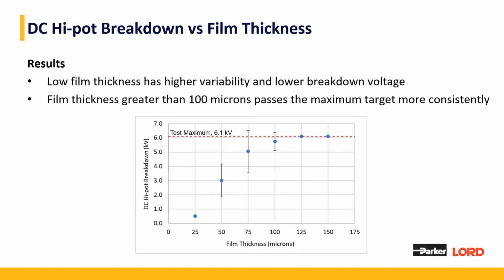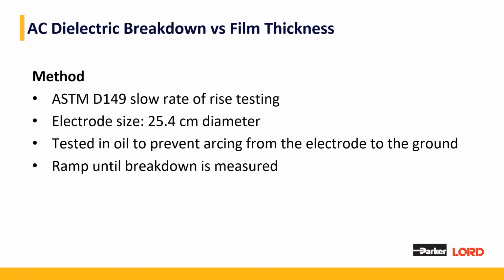Another important note is that the test maximum for this hypot sweep is 6.1 kilovolts, and all samples tested at 125 microns and 150 microns exceeded this limit and did not show a breakdown failure. This same test was repeated using ASTM D149 to measure AC dielectric breakdown versus film thickness. When testing insulative materials, we test in oil to prevent arcing from the electrode to the ground, ensuring the breakdown measurement is through the material being evaluated.